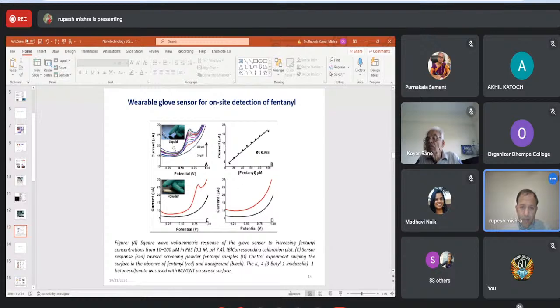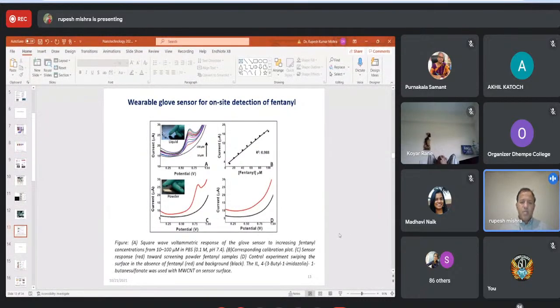You see here, we have got a nice calibration curve here, right? And then we have detected in powder form, and as well as in the blank sample when there is no fentanyl. So you don't see any peak here, right? This is the oxidation peak of the fentanyl. Normally, when fentanyl oxidizes, it will convert to the norfentanyl, and this is the oxidation of norfentanyl, basically, right? So this is another example of glove-based biosensor.